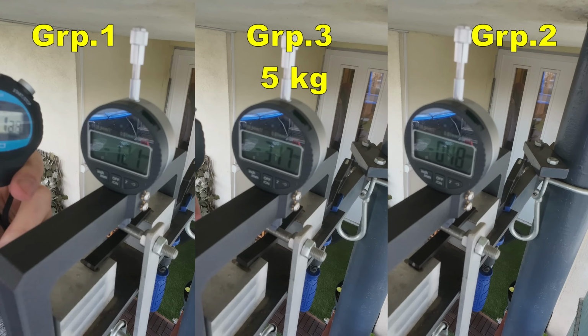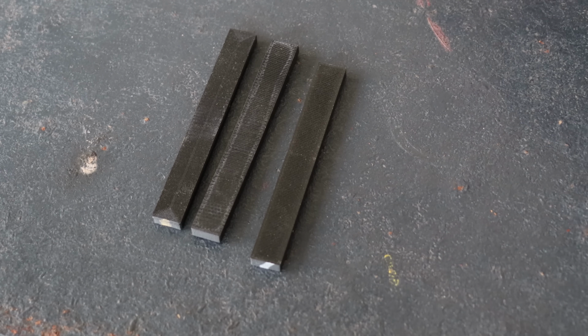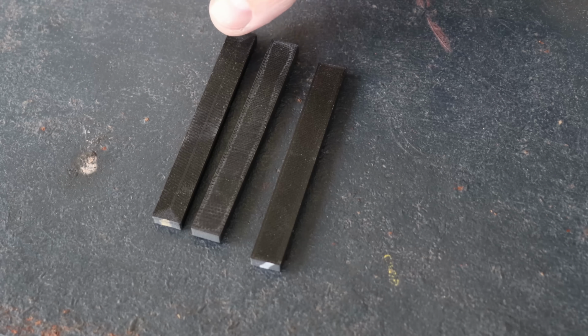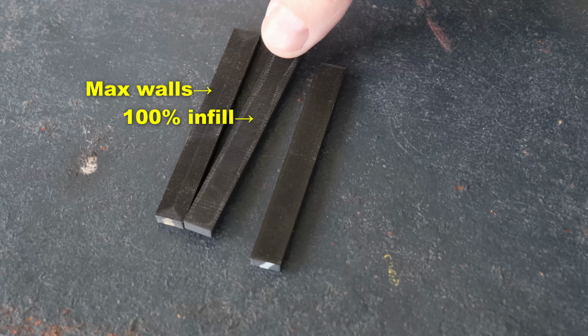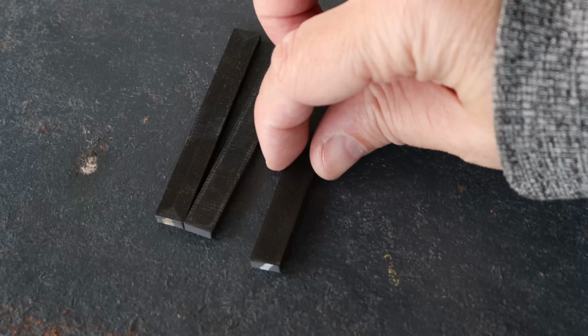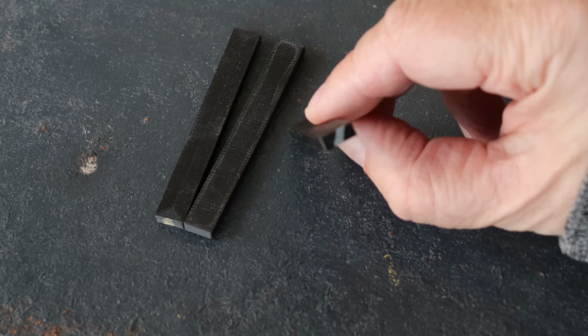Here you can see all three objects side by side, and the glass fiber is on the right side, the strongest, but pay attention to the one in the middle, how much bigger deformation it has compared to group 1, which is quite a big surprise. It was surprising to see so big a difference here between groups 1 and 3. And this one reinforced with glass fiber is completely straight even now.